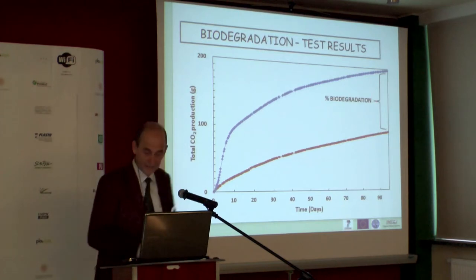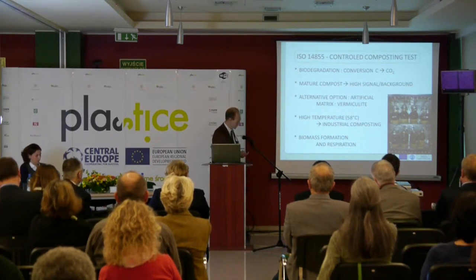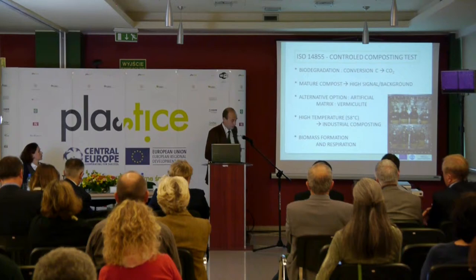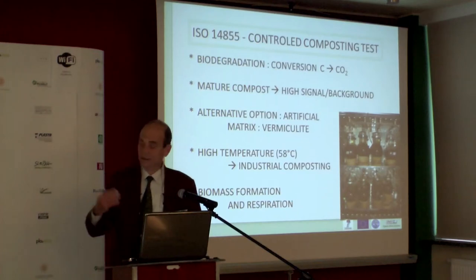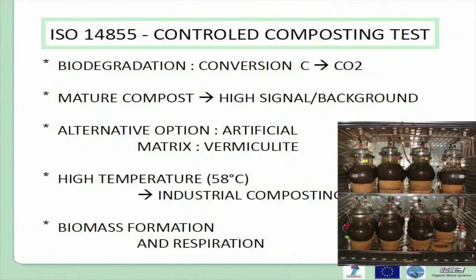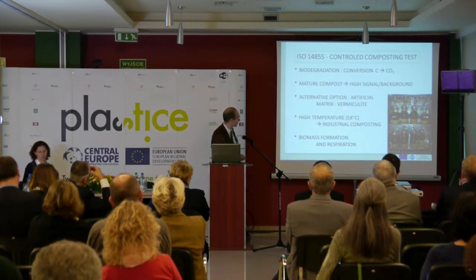In this project, with regard to composting, we will mainly focus on two methods. One is ISO 14855, a controlled composting test method to measure the conversion of carbon to carbon dioxide. Normally this test is run with mature compost as an inoculum to have a high signal-to-background ratio, but by working with mature compost we deviate from reality, since in reality we work with fresh waste. This can have an impact for some polymers. Another option is to work with an artificial matrix.